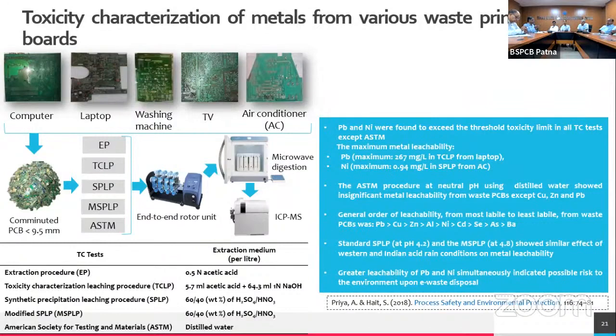Let us say, looking at the pH of the acid rain condition in India, we looked at the last 15-20 years of acid rain pH data from the designated stations all over India. And what we see is that acid rain pH in Indian conditions is typically 4.8. Then we performed this test. What we have seen is that if you subject the material to the standard or the modified procedure,